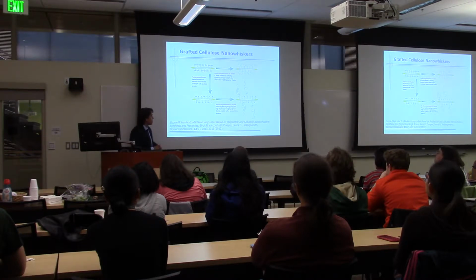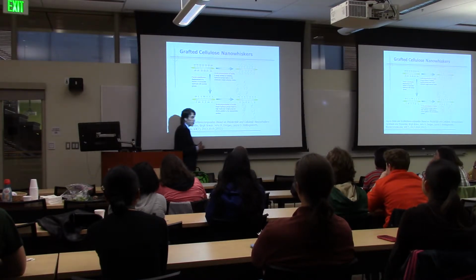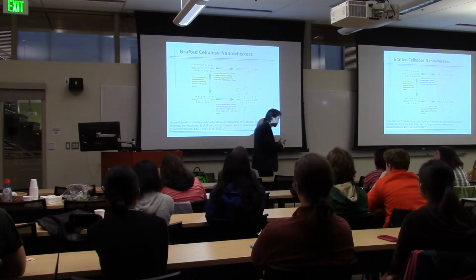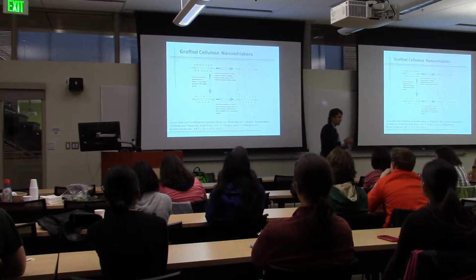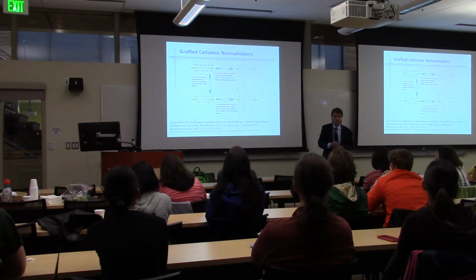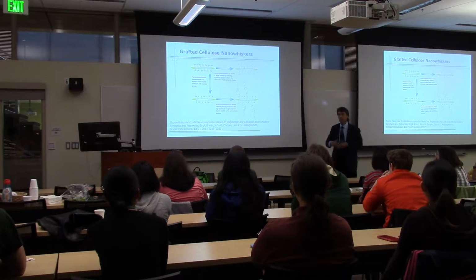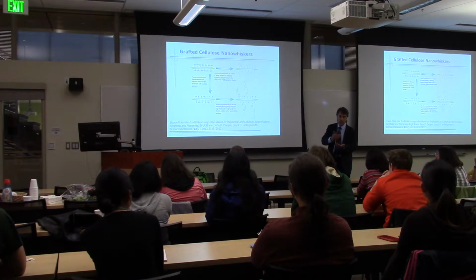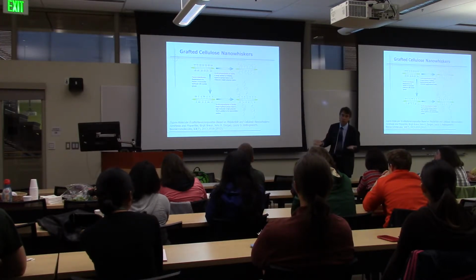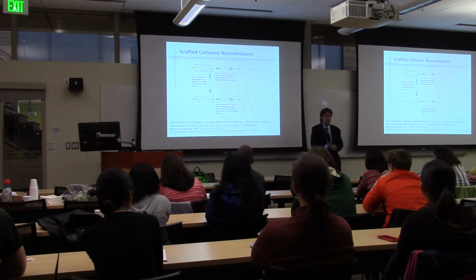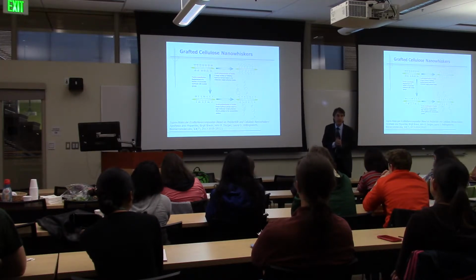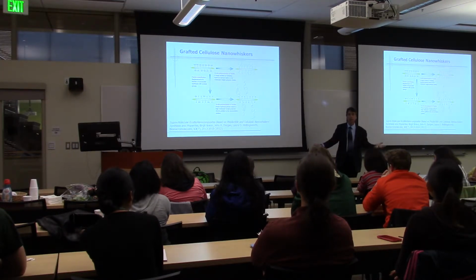And so that means that we can actually control the number of acetate groups on the surface, which is really what we're after. And why are we after that? Well, I take it Travis teaches polymer, yeah? So I should ask all of you that have had Travis's class, why is that so important? Well, the issue is if you have a lot of initiating groups compared to the amount of monomers you have, and each initiating group starts a chain, then the monomers per initiating group is a low number. It's a small number. And so you get low molecular weight. And so, of course, that was the problem that we were having when we first tried to do this, even with the hydrochloric acid-derived cellulosic nanowhiskers, we just had too many hydroxyl groups.